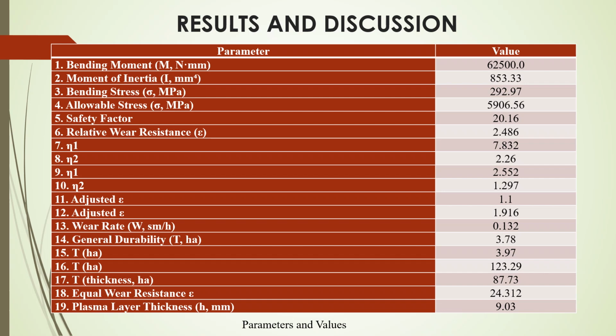Bending stress was about 293 megapascal, while allowable stress was much higher, around 5,906 megapascal, giving a safety factor, as you know, of 20.16. This means the material can safely withstand field loads. We also measured relative wear resistance, which was 2.486, and the wear rate was very low at 0.132. The general durability was calculated as about 3.8 to 4 hectares, showing good working performance. Finally, plasma layer thickness was measured at 9 millimeters, which contributes to improved resistance and longer service life.